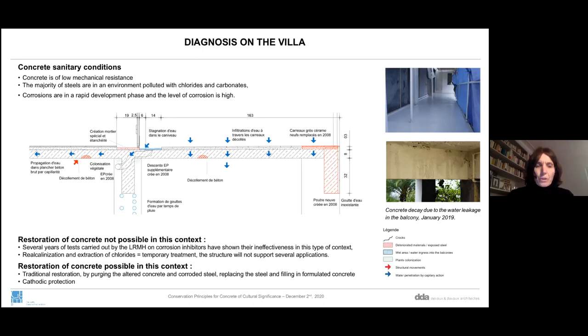So we tried to find a new concept of restoration. There were not many possibilities in this context, where the concrete was very, very much polluted. Corrosion inhibitors were not efficient in this type of context, and there was also no possibility of re-alkalization or extraction of chlorides. So the only interventions were traditional restoration, which means purging the altered concrete and corroded steel, replacing the steel and filling in with formulated concrete, or cathodic protection. We were quite interested in cathodic protection because it is a very long-lasting restoration of 50 years normally, and even more, we don't know yet, it's not so old. And since the condition of the concrete was so poor, it seemed very interesting to us.